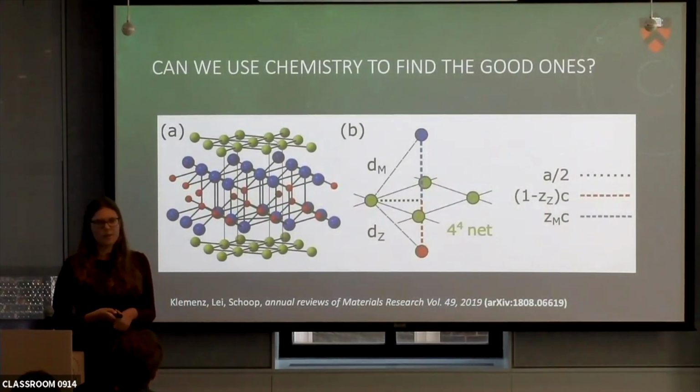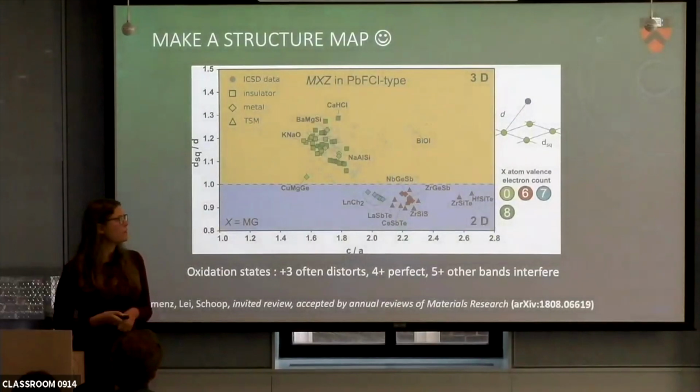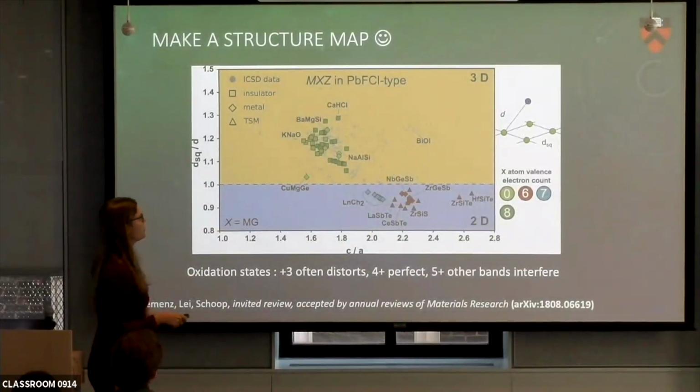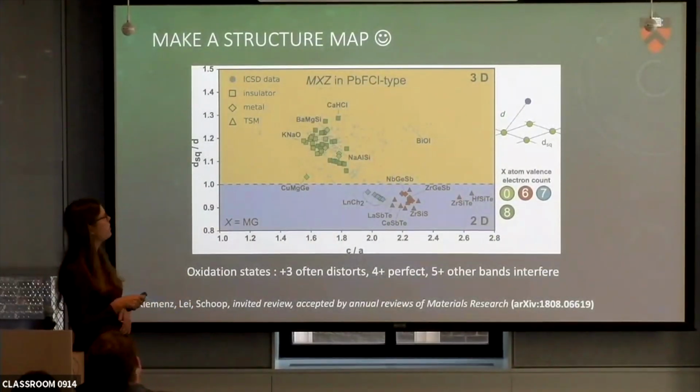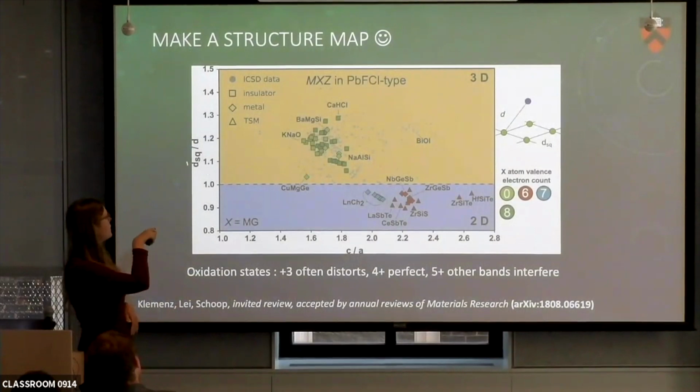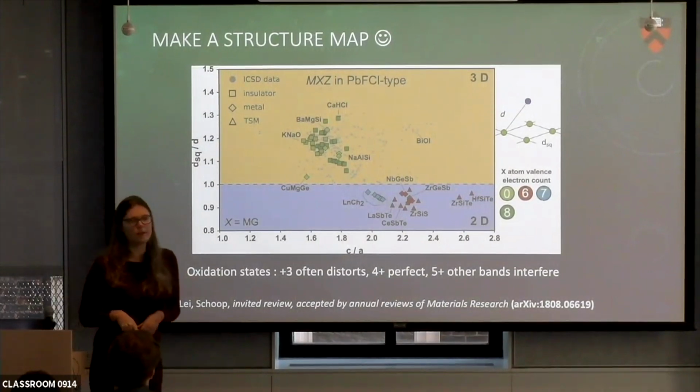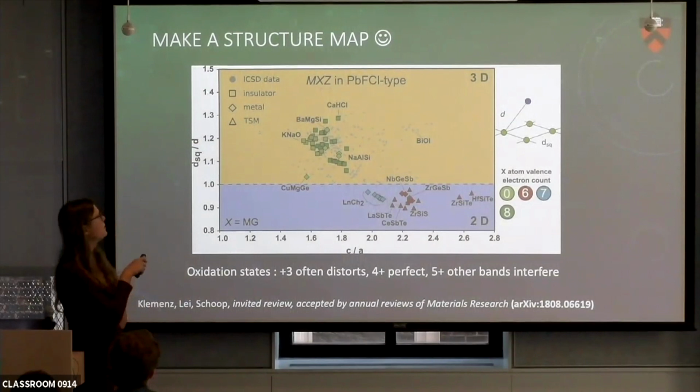Okay? So we just went and looked at all the CIF files and plotted these bond distances, and we made this rather complex map, but this distance factor is plotted right here on the y-axis, and whenever we are below 1, we fulfill the rule of having a chemical delocalized bond, and when we are above 1, we violate the rules.